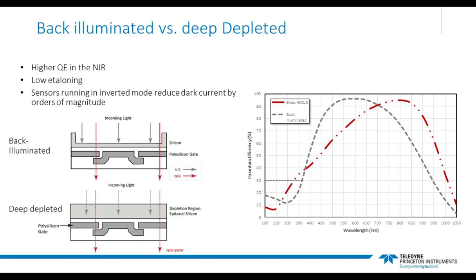So for achieving even higher detection efficiencies in the NIR, back illuminated deep depleted sensors have been developed. So these sensors use a much thicker silicon depletion region. So instead of 13 microns, about 40 or so. So more light in the NIR can be absorbed. So here on the right, the figure compares the typical quantum efficiency of a standard back illuminated and a deep depleted device. And so you can clearly see that the efficiency is increased for higher wavelengths. An additional benefit is that effects of etaloning are much diminished in such devices as well.